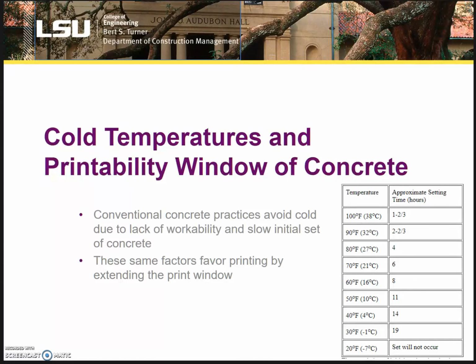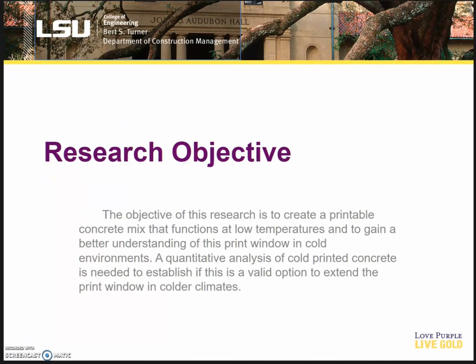to create shapes. But when we're talking about 3D printed concrete, this is actually somewhat advantageous as it increases the initial yield stress of the concrete, and workability can be altered with admixtures. And because it has a longer set point, the print window is extended as the set time goes from around 4 to 5 hours to around 20 at very low temperatures.